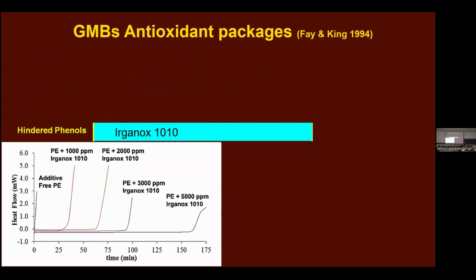We take a specimen, we heat it, and we heat it in a nitrogen environment. Then we introduce oxygen. And the OIT is how many minutes it takes before the polymer starts to degrade. The antioxidants are protecting the polymer, and then they're gone, or they're deactivated. And suddenly, the polymer starts to degrade. That's an exothermic reaction, and so we see the heat go up. And you can see as we increase the Irganox 1010 from 1,000 parts per million to 5,000 parts per million, we increase the time it takes. So at 5,000, we're at about 160 minutes of OIT. Okay, that's nice.